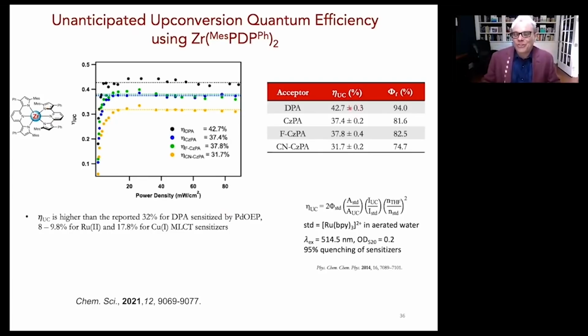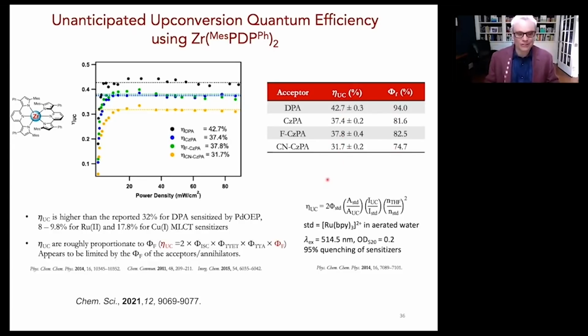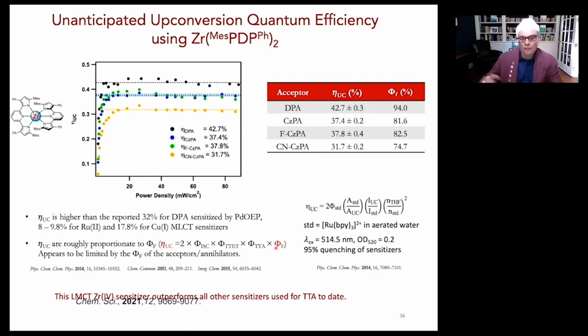And as I told you, the upconversion efficiency seems to scale with the fluorescence quantum yield. So what I told you earlier was the fluorescence quantum yield seems to be the thing limiting this value, which is kind of amazing to us. And that's what I tell you here. And then this zirconium-4 sensitizer just simply outperformed all other molecular sensitizers we've used or anyone else has used to date. So pretty remarkable stuff.